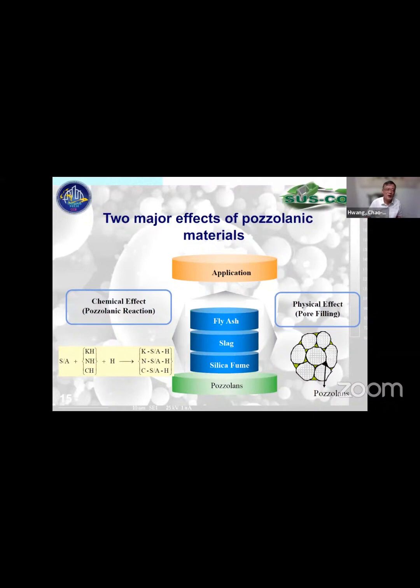Looking at the chemical effect on the left-hand side: fly ash or bottom ash, by adding calcium hydroxide and sodium hydroxide, together with the concrete cement's calcium hydroxide and some water, they react and can form a lot of gel and crystal. So that's the reason concrete can last longer, because of the reaction. So what we are doing, next please.